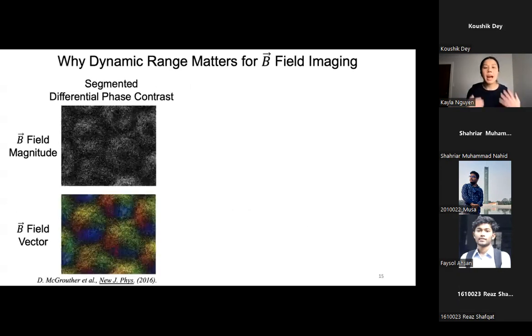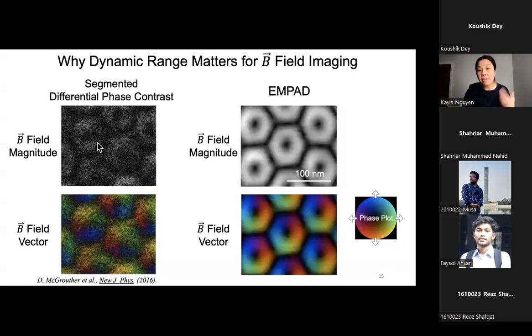So how does our technique compare to the traditional techniques using a CCD camera in the electron microscope? What people typically do in electron microscopy is take a CCD camera and cut it up into quadrants, for example, top and bottom or left and right. Because the CCD camera can only detect up to 25 electrons, we can still see information related to the skyrmion, but it doesn't have that much dynamic range. With the EMPAD, with these new detectors, we do get more information than what we had before. And so dynamic range matters a lot.